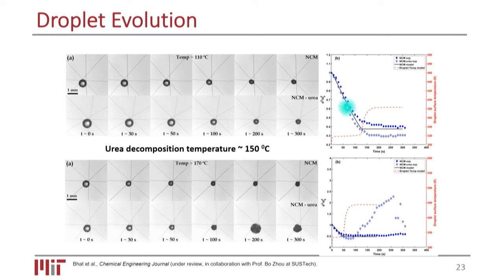we have NCM and we have NCM with urea. Both of them, and this temperature is selected to be 110, which is slightly higher than the boiling point of water, which is the solvent in this case. But urea would stay in the solution without being decomposed. So we roughly have that, and the diameter would be roughly constant after the solvent goes away. However, by increasing the temperature to 170 Celsius, where we trigger the thermal decomposition of urea into gases, we see that the neat droplet still follows the D square law, just happening in a faster manner, right? But for the urea, we start to see the expansion, et cetera. And on a closer look at the figure, we see the formation of some bubbles.